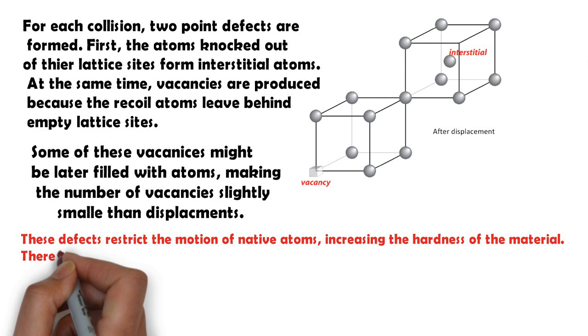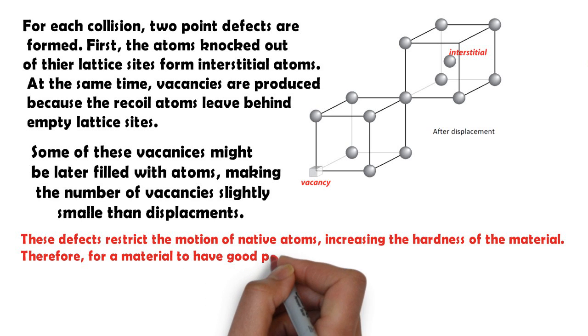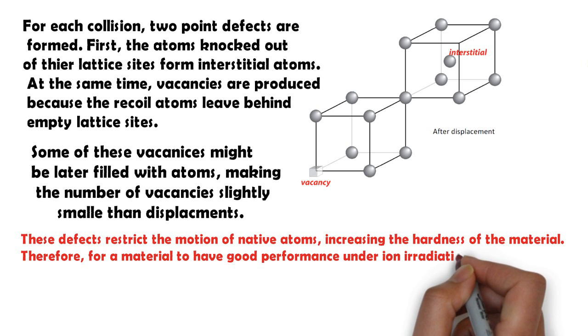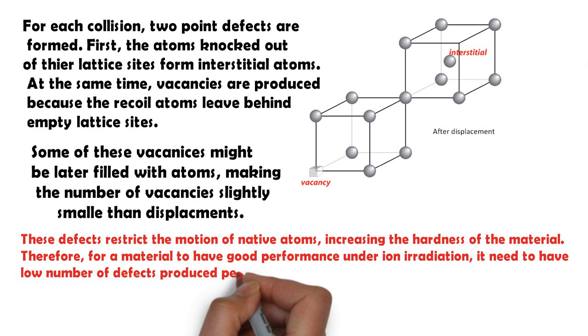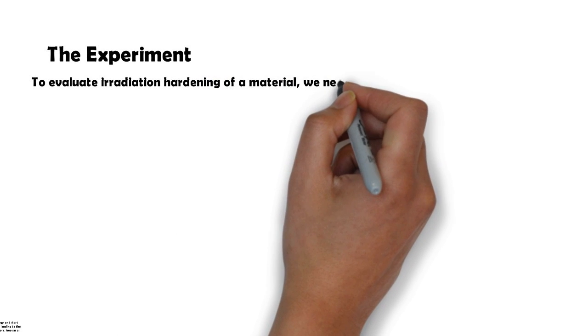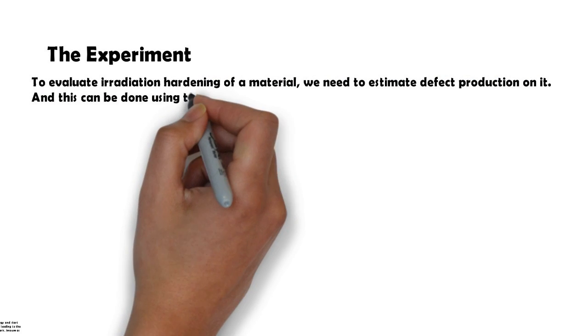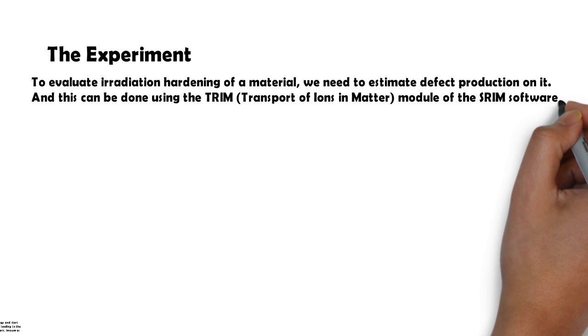Therefore, for a material to have a good performance under ion irradiation, it needs to have a low number of defects produced per ion or have the defects restricted near the surface. To evaluate irradiation hardening of a material, we need to estimate defect production in it. And this can be done using the Transport of Ions in Matter software, also known as TRIM.